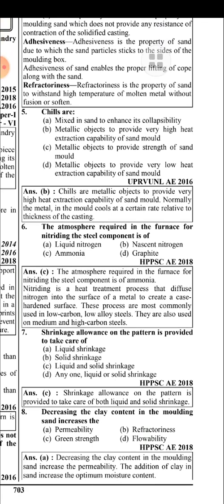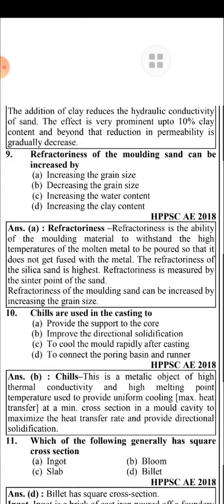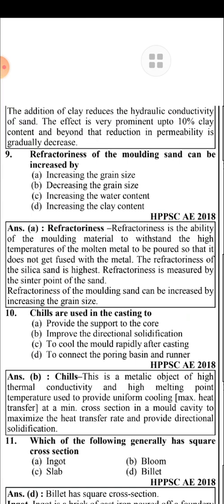Shrinkage allowance on the pattern is provided to take care of both liquid and solid shrinkage. Decreasing the clay content in the molding sand increases the permeability. The addition of clay in sand increases the optimum moisture content. The addition of clay reduces the hydraulic conductivity of sand. The effect is very prominent up to 10% clay content, and beyond that the permeability gradually decreases.